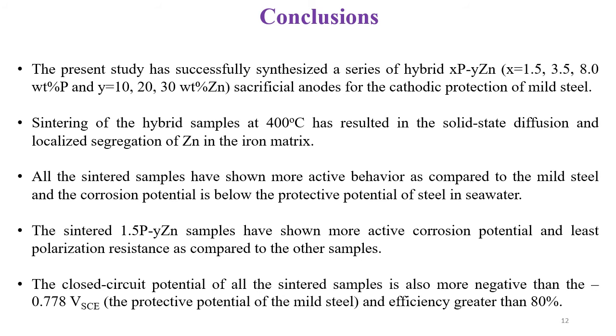So based on this, we can conclude that we have successfully synthesized a series of hybrid samples based on this composition, and all the samples have shown more active behavior as compared to the mild steel, and the corrosion potential is much below the protective potential of steel in seawater. The 1.5% composition shows comparatively more active behavior as compared to the other hybrid samples, along with the closed circuit potential.